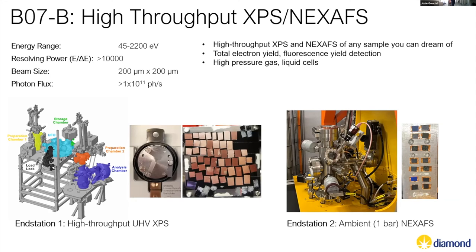There are some systems, so we've got quite a lot of work on ceria. We use the resonance spectroscopy there because you can really pretty much fit the cerium 3d spectra. If you want to talk about multiplet effects, you know all about that. You can go to the valence bands and look at the 4f of cerium, and you can excite it with two slightly different energies, and you're really sensitive to 4+ or 3+. Now it doesn't give you an absolute measurement, but it will give you a relative measure. So on that we used it pretty extensively. So here with 120 eV, excite the 3+.